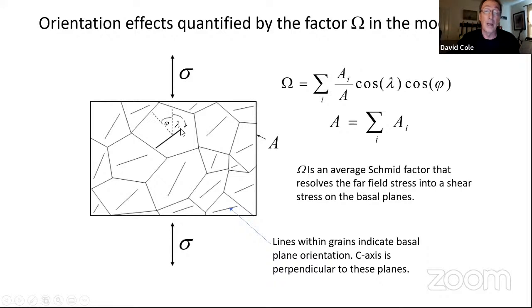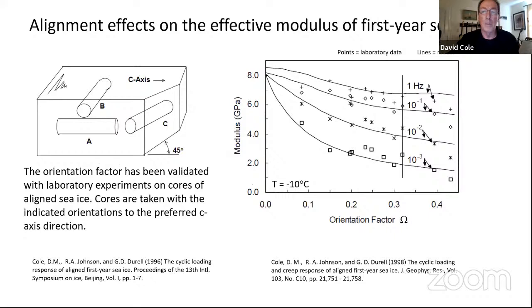We've done a lot of work there in validating this, and it's very solid theoretically and both in terms of validating the basic concept that the shear stress on the basal planes is in fact what's driving the inelastic behavior. But we've looked at this for quite a few specimens, and it's held up well. So one then takes the orientation data on how your individual basal planes are oriented. You calculate this, what I'm calling omega here, which is just this average Schmid factor. This is kind of tedious, but can be quantified if you take highly aligned cores and then slabs of ice and take cores that are oriented at specific directions to that alignment.